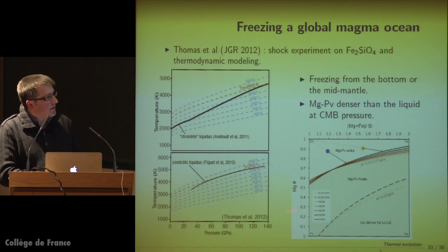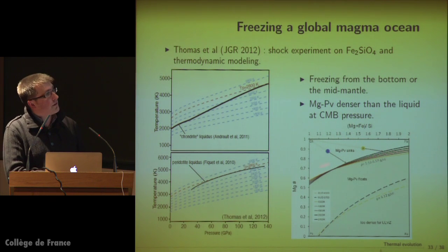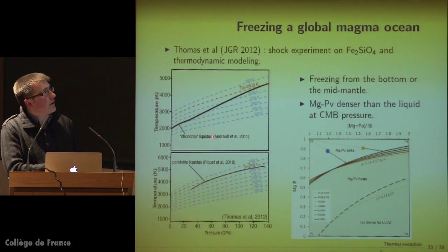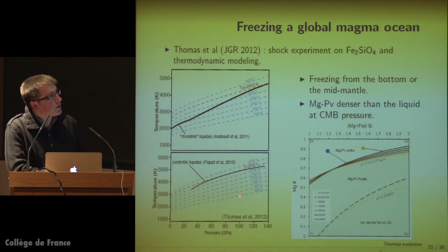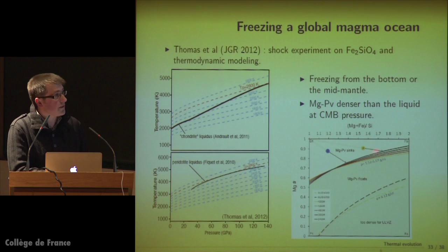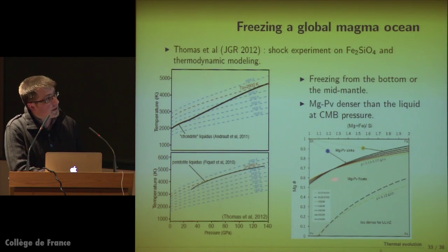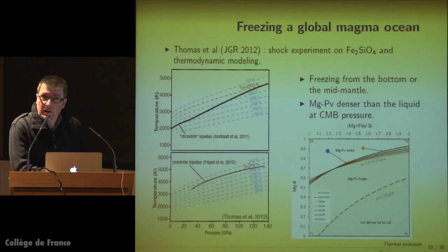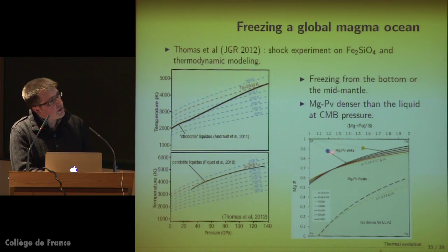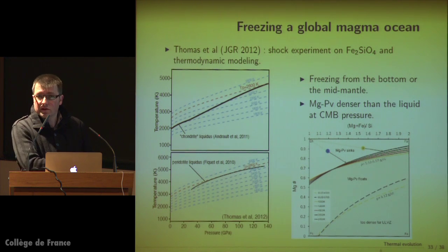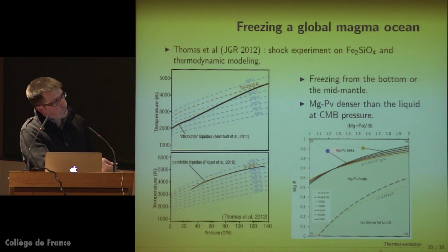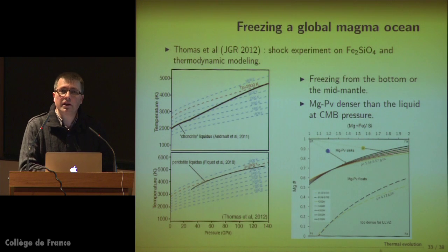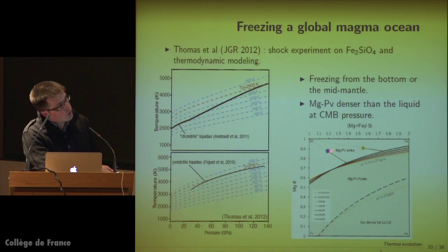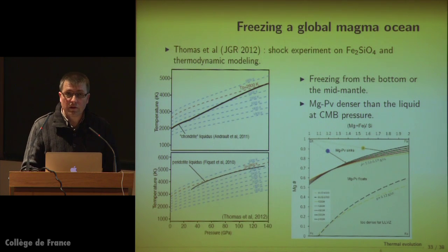To end up, in this paper they also computed the density of magnesium perovskite compared to the liquid at CMB pressure, and depending on the composition that they use, in both compositions here, they find that the magnesium perovskite that crystallizes at the bottom of the mantle from such magmas would actually sink, would be denser than the liquid. So that would go against our scenario. But of course, if you start by crystallizing magnesium perovskite here, you take out essentially the magnesium perovskite end member from the liquid, then you enrich the liquid in iron compared to the solid. So the liquid would evolve in this direction, where it would actually become denser than the solid.